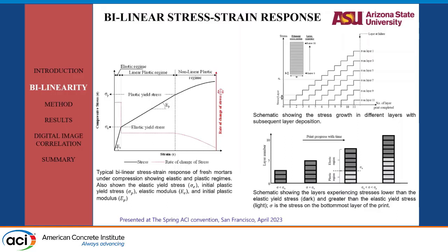In this model, a printed system will be a composite system where you keep on building filaments. In this example, we are assuming that the elastic yield stress is reached when there are 5 filaments above a certain filament. When you start building a structure, the elements remain in an elastic response regime till at a point there are enough filaments on top of the lowest filament that the lower filaments start to go into plastic response. As it keeps on building till failure, some filaments in the lowest region will be in plastic response, while some on the top will be in elastic response.